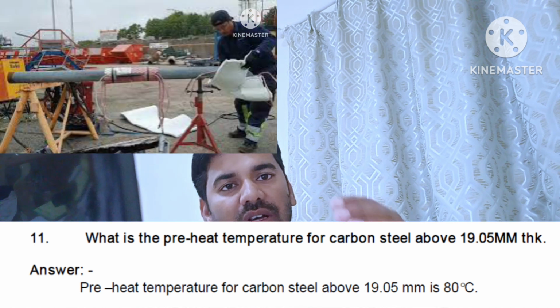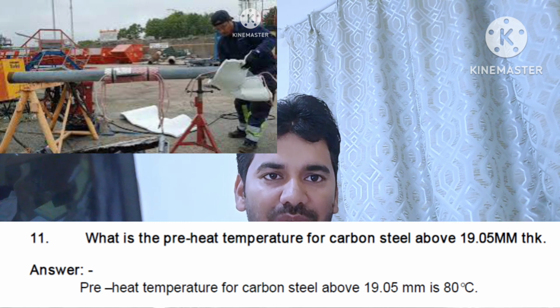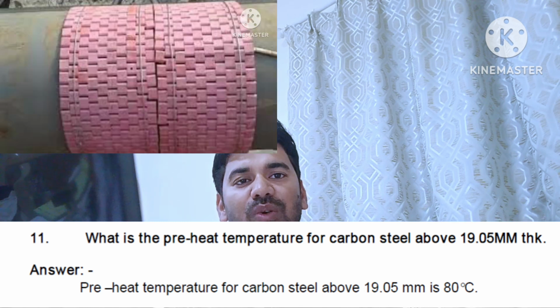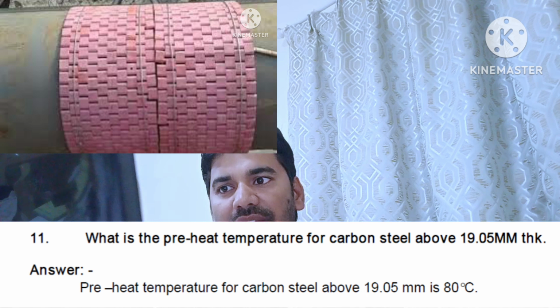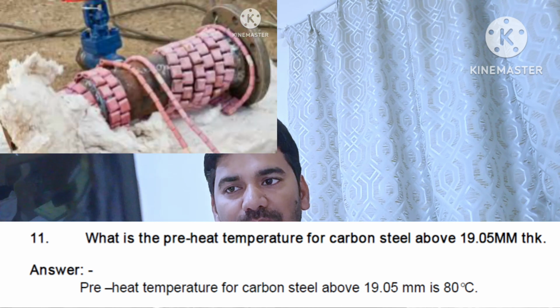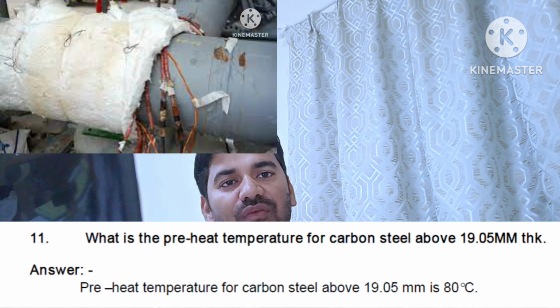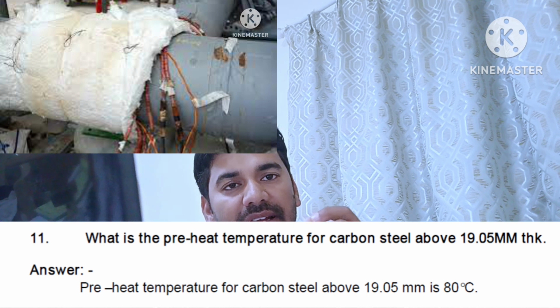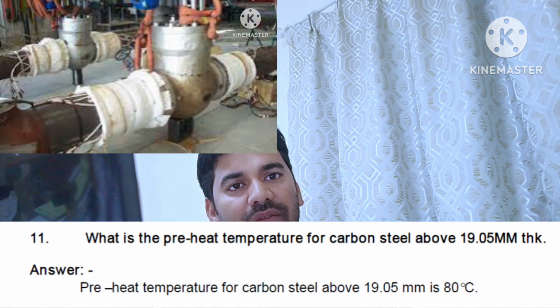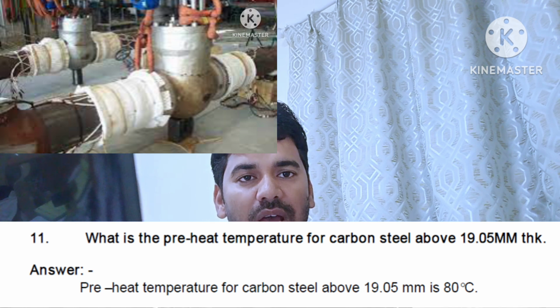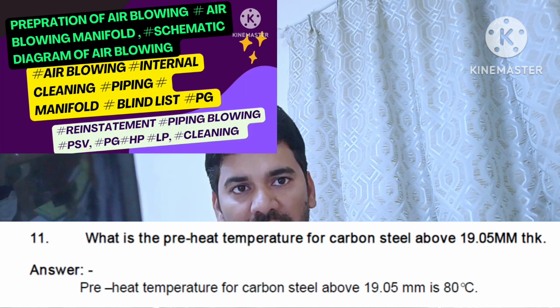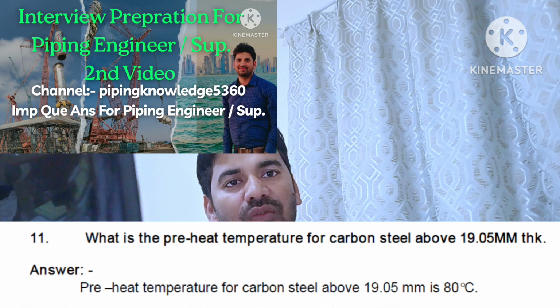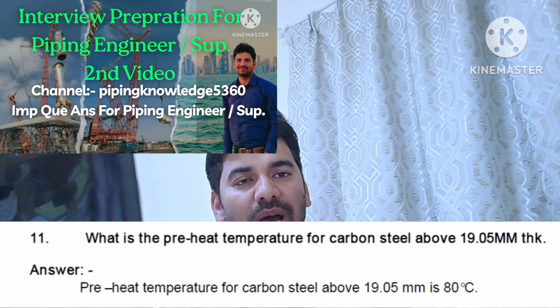But if the thickness is 19.05 mm or more, then you need to do preheating before you start welding, and the preheating temperature is 80 degrees Celsius. For normal pipe, if you are working in a cold place like Russia where the temperature is always minus, then for any pipe you want to weld, the minimum pipe temperature must be 10 degrees.